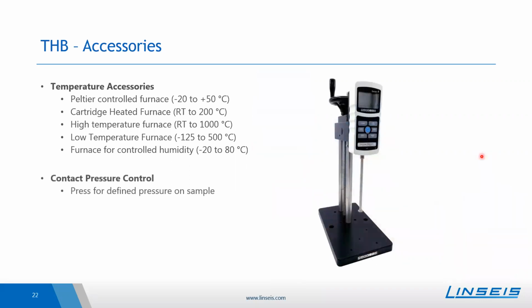There's also a tool for the control of the contact pressure. For example, for foams or elastic materials, one can realize pressure-dependent measurements, as for elastic or soft materials the thermal conductivity strongly depends on the contact pressure. I have put in an application example a few slides later, where you see how strongly the thermal conductivity can depend on the contact pressure.